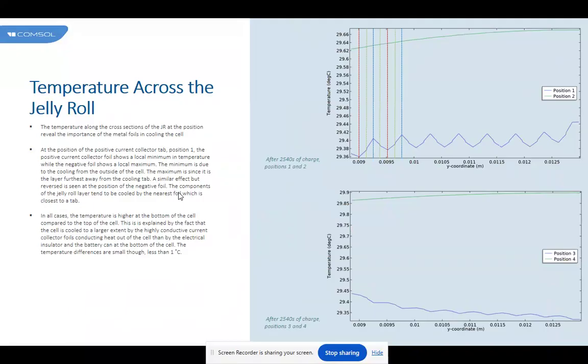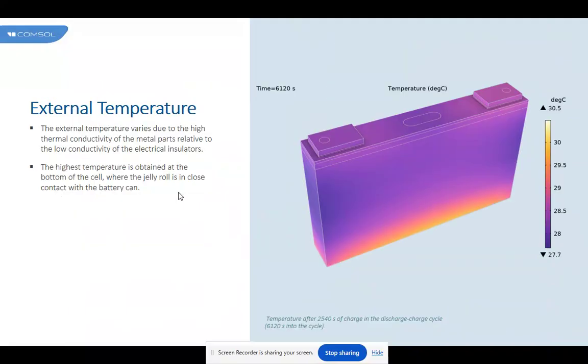The components of the jelly roll layer tend to be cooled by the nearest foil, which is closest to the tab. In all cases, the temperature is higher at the bottom of the cell compared to the top of the cell. This is explained by the fact that the cell is cooled to a larger extent by the highly conductive current collector foils conducting heat out of the cell than by the electrical insulator and the battery can at the bottom of the cell. The temperature differences are small, less than 1 degree centigrade.